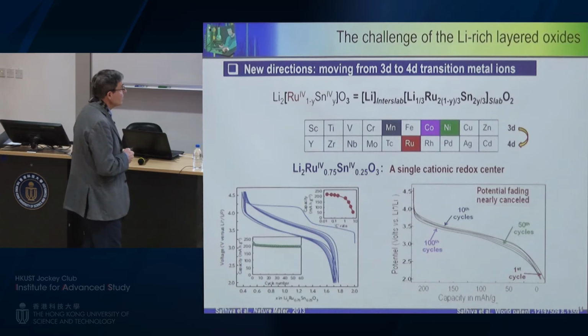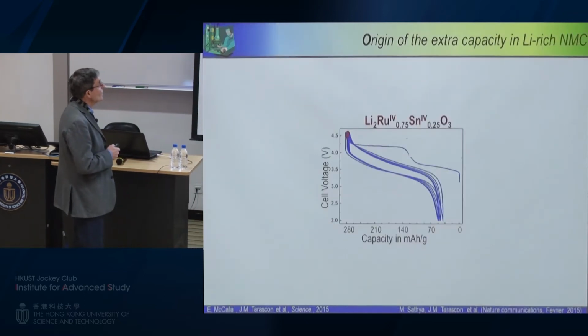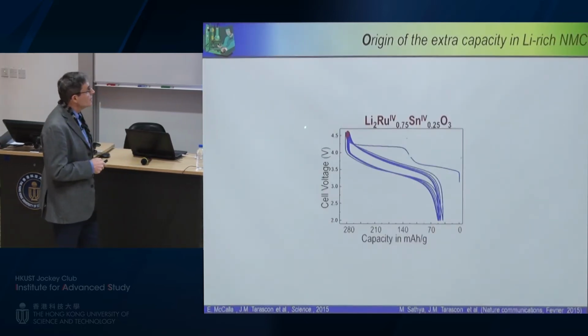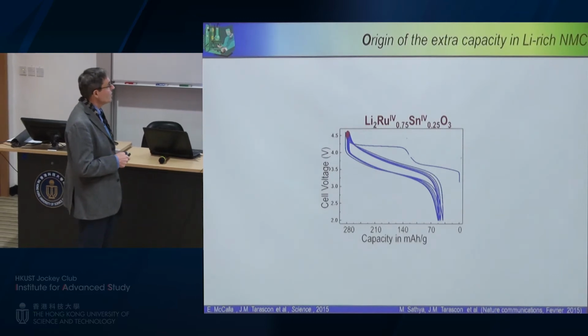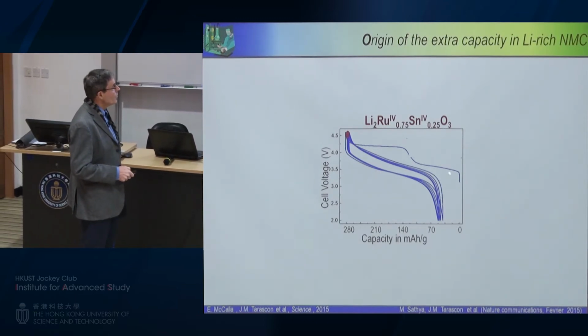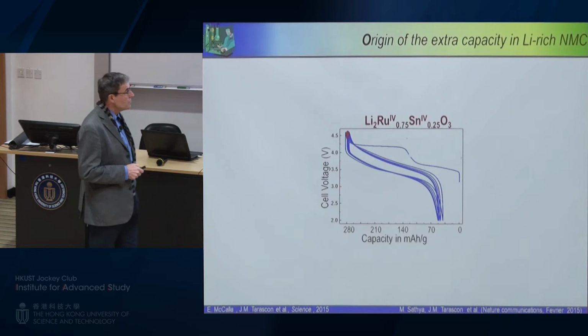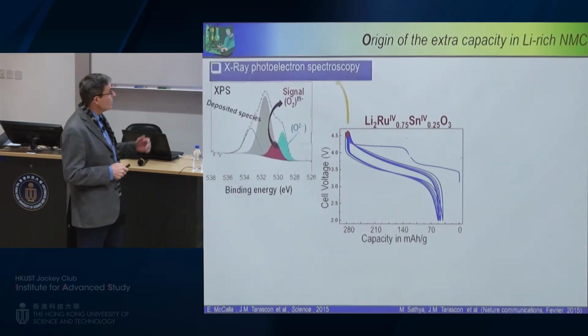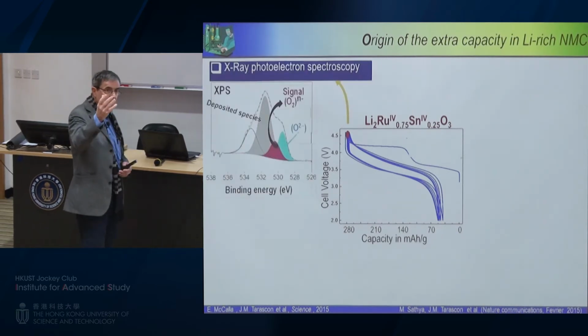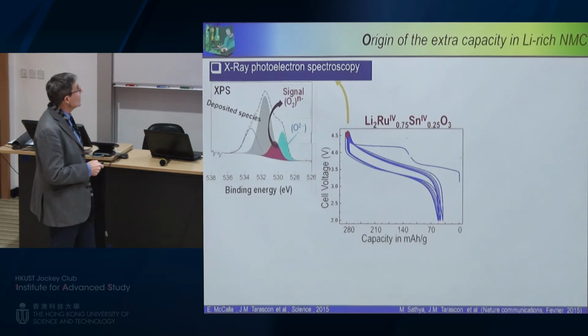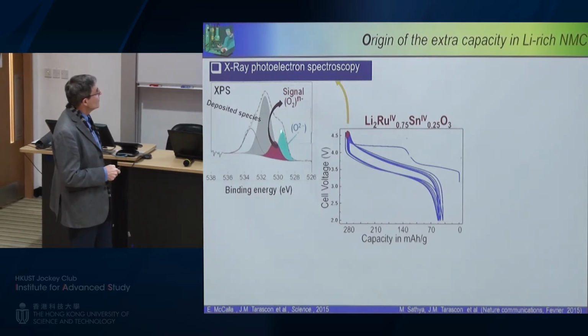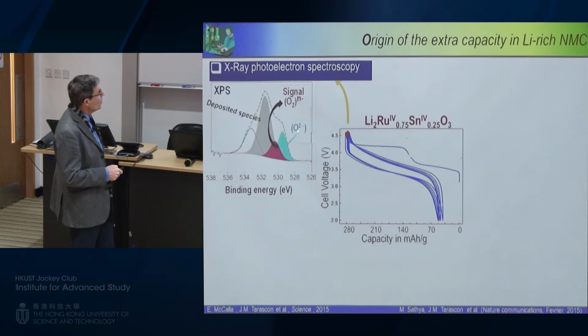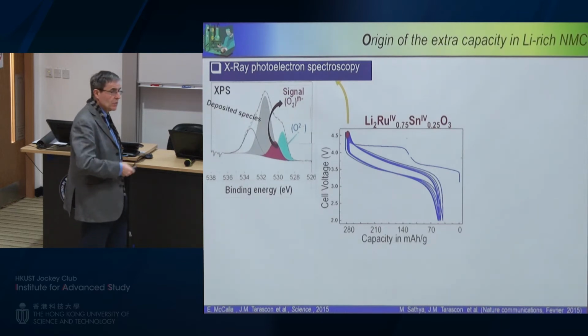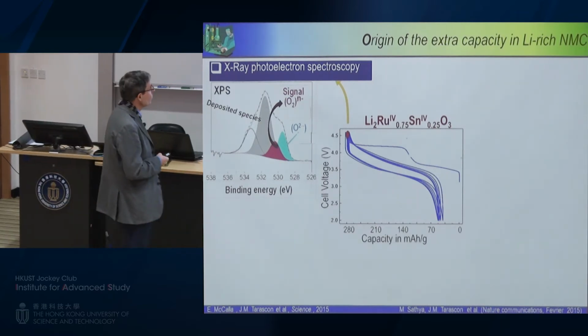So to do this, we have done several types of measurements on the samples that were either charged or discharged. And here you can see a charged sample. We are going to observe this by XPS, which means you are looking at the binding energy of the electron. We look at the O 1s core spectra, and you can see that we have the classical O2- peak associated with the crystal oxygen.